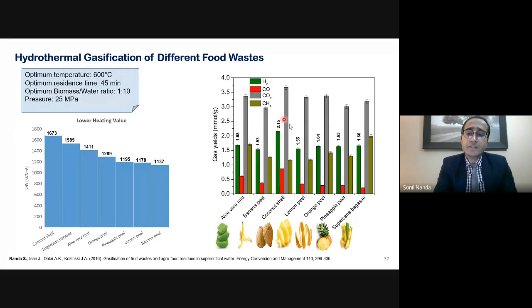Now, coconut shell resulted in high yields of hydrogen because of the presence of more lignin content in it. Lignin is quite high in coconut shell. Therefore, lignin resulted in easy solubilization in supercritical water and resulted in the yield of hydrogen. Now, the lower heating values of the gases are shown here. Once again, the gases obtained from coconut shell had the highest heating value, followed by sugarcane bagasse, aloe vera rind, orange peel, pineapple peel, lemon peel, and banana peel. This trend almost reflected the trend of the hydrogen yields obtained from the hydrothermal gasification.